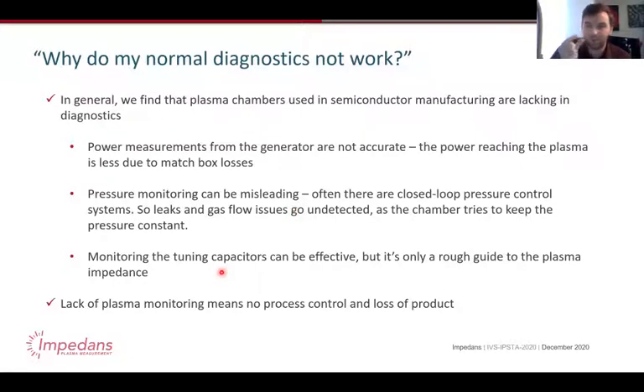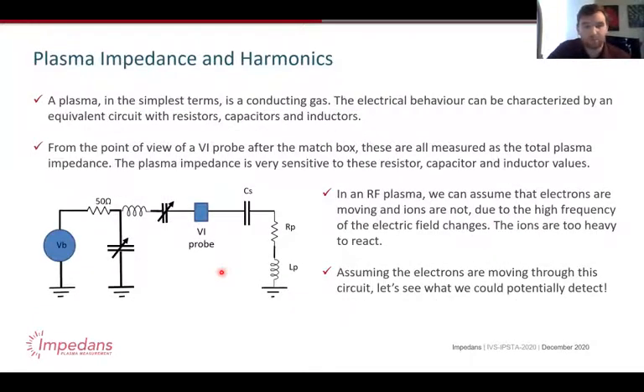Some people monitor the tuning capacitors in their radio frequency network, the matchbox, which is a rough measure of what's called the plasma impedance, but it's not good enough for 5 nanometer and 3 nanometer, basically. If you don't control it, you're going to lose the products. So what I want to introduce is what's called plasma impedance, and it's actually where the company name came from.